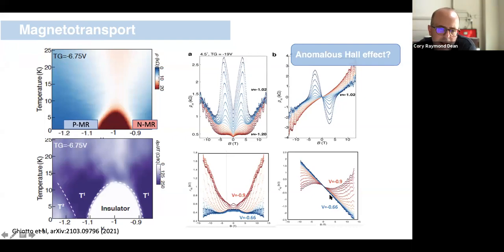So this is early data. This is more recent, and we're trying to figure out what this exactly means. One generous interpretation of this Hall data might be that it indicates something like an anomalous Hall response. In that interpretation, it might be indicating that we have some ferromagnetic ordering on the overdoped side, and that we transition to a different behavior on the underdoped side might indicate that whereas overdoped is ferromagnetic, underdoped may not be ferromagnetic. So that again is almost speculation at this point. I wouldn't say our data is really evidence of that. It's an interpretation possibly of our data.